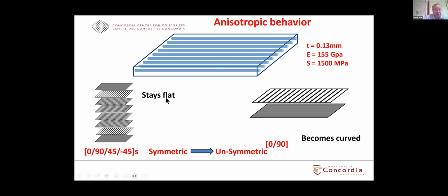You start with a flat layup, and at the end you obtain a flat laminate. But the case of 4D printing of composite is that we want the flat laminate to become a curve. So that's why we use unsymmetric, something like a 0-90 laminate configuration. That way you start with a flat stack of the pre-preg, and by the time you cure it, you cool it, you obtain a curved structure.